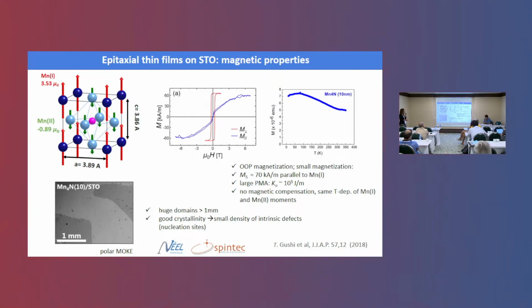What I forgot to say is that the net magnetization is parallel to manganese 1, so perpendicular here. VSM SQUID measurement shows also out-of-plane magnetization, with a very small magnetization, since it's a ferrimagnet. Just to give you an idea, 20 kA per meter corresponds to more or less 15 times less than the magnetization of 1 nanometer of cobalt in the systems that we are used to. Large PMA, and just to make sure, there is no magnetic compensation temperature because the evolution of the two manganese sites is the same in temperature.